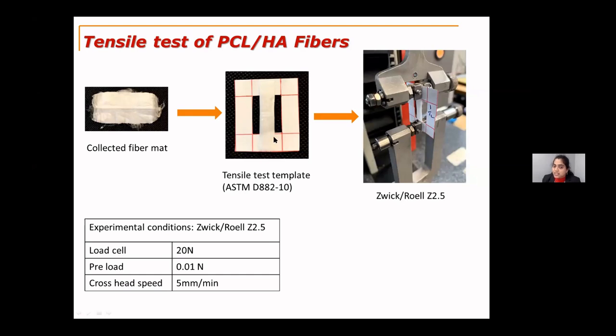And we tested this fibrous mat using the Zwick Roell Z2.5 universal mechanical testing machine, which is equipped with a load cell of 20 newtons. The minimum load it can measure is 0.001 newtons. So we applied a preload of 0.01 newtons with a crosshead speed of 5 millimeter per minute. And these polycaprolactone fibers especially have a high stretchability. It exhibits around 350% of strain.